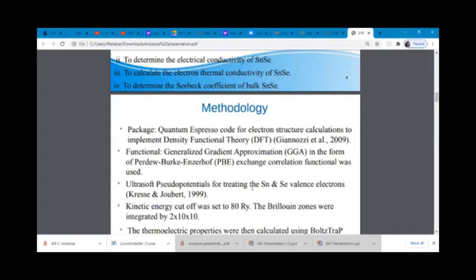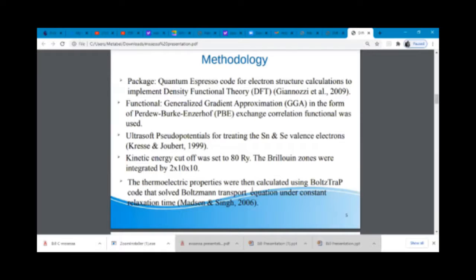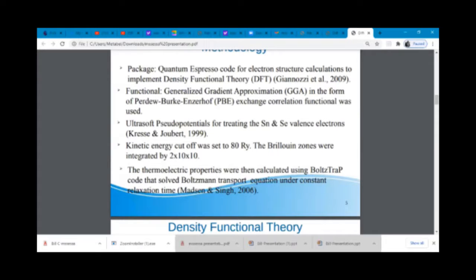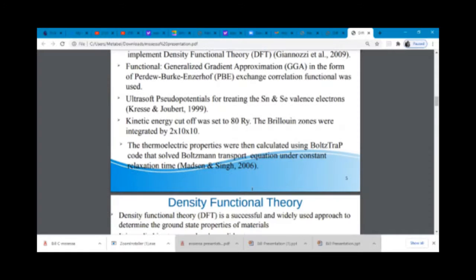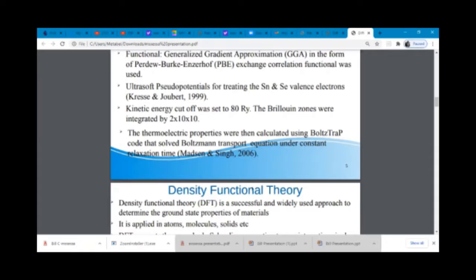The methodology employed used the Quantum ESPRESSO code within the framework of density functional theory for electronic structure calculations, and a generalized gradient approximation parameterized in the form of the PBE exchange and correlation functional was used. The ultrasoft pseudopotential approach was used for treating the valence electrons, and the kinetic energy cutoff was set to 80 Rydberg. The Brillouin zone was sampled by a 2 by 10 by 10 mesh grid. The thermoelectric properties were then calculated using the BoltzTraP code that solves the Boltzmann transport equation under the constant relaxation time approximation.